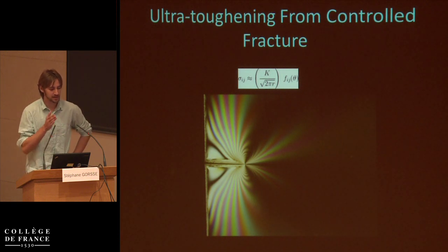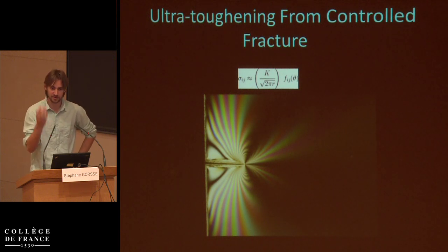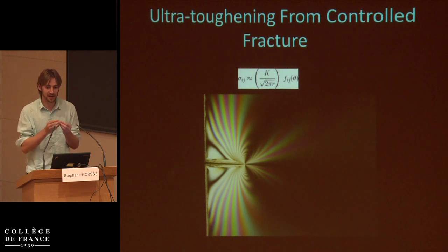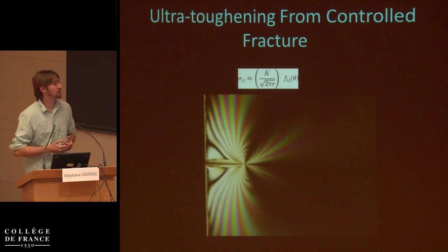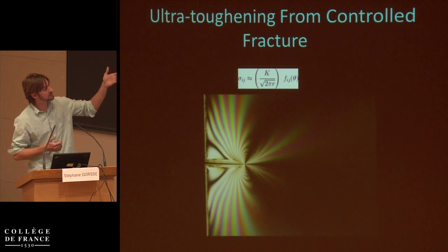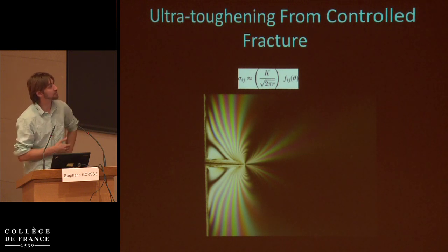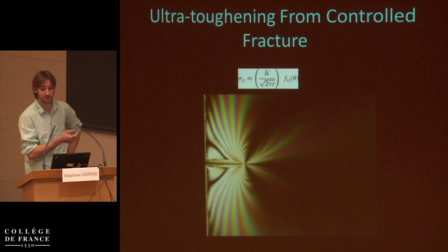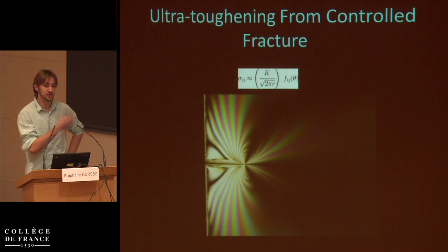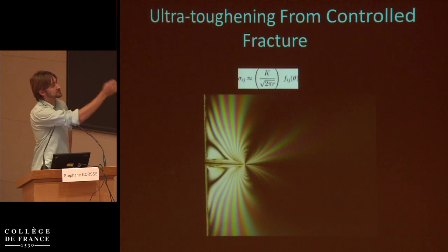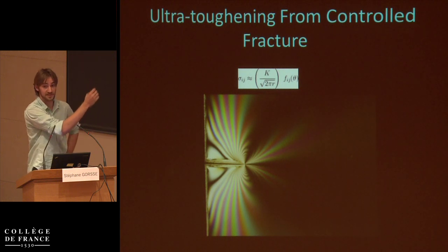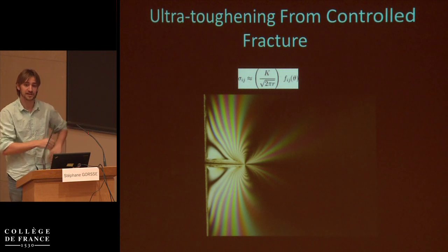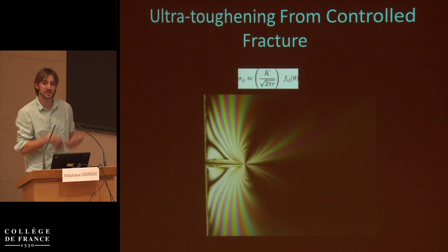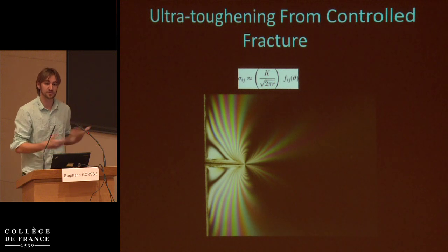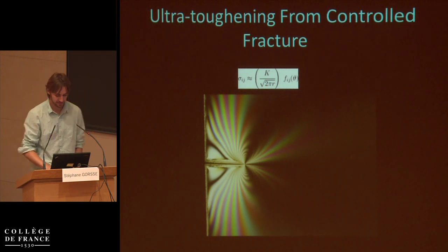in order for that mechanism to work, you will begin severing fibers if the local stress exhibited by one fracture isn't able to hop to a new pore. That's simply because the stress surrounding a fracture is inversely proportional to your distance from the fracture front. So you'd always need a new pore to be located next to, or sufficiently close to, your fracture front, such that it feels a sufficiently strong stress to exceed the strength of the material to initiate a new fracture and to arrest the old, because you're relieving the stress of the previous fracture.